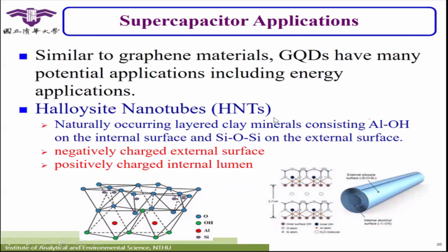The characteristic of this material is that it contains aluminum oxide on the inner surface, and silicon dioxide on the outer part. From soil chemistry, you always know the layers must balance. Alumina is 3+, silicon is 4+. So when they are in the same material, most of the time your silicon will become negatively charged, and your aluminum will become positively charged. This material has been widely used to absorb metal ions in soil. That is quite common. But now we use this for energy application. Since their outside is negatively charged and inside is positively charged, we can try to let the electrons get inside, so they can store some energy here.